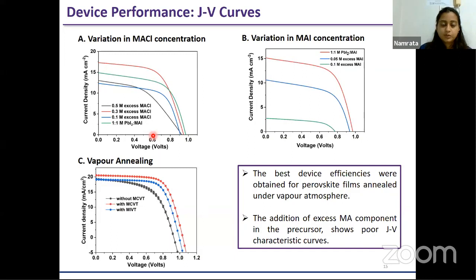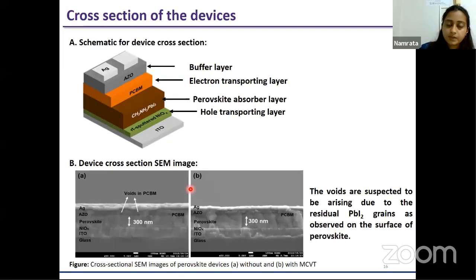But comparing it to the vapor annealing condition, we see that the performance increases manifold, and we get the best JV curve for the perovskite solar cells which have been annealed under a methyl ammonium chloride vapor atmosphere, and which have a stoichiometric ratio of 1:1 for the PbI2 and MAI. So in summary, we see that addition of excess MA component in the precursor shows a poor JV characteristic curve. And when we have the precursors in a 1:1 ratio, we have the best device performance.